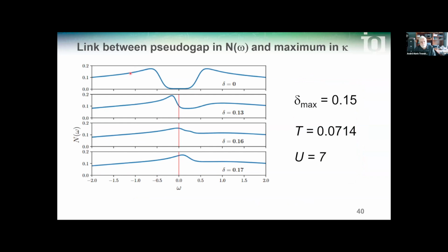Okay, let's do that slowly. This is a single particle density of states as a function of frequency. At half filling, for that temperature, the pseudogap in the density of states is almost a real gap. As the hole doping increases, 13, 16, 17%, the Fermi level moves to the lower peak. It's only at 17% doping that the pseudogap has completely disappeared from the density of states. And the maximum of compressibility here is at doping 15, so somewhere here.